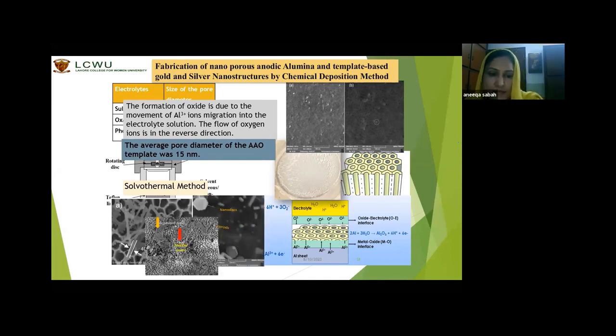Secondly, silver nanoparticles were tried, but they were unable to get into the pore. So pore size actually mattered with the metal nanoparticles—the metal nanoparticles and the pore size should match so that you can get your materials inside the pores. But for gold, we were able to get nanodiscs and nanorods.